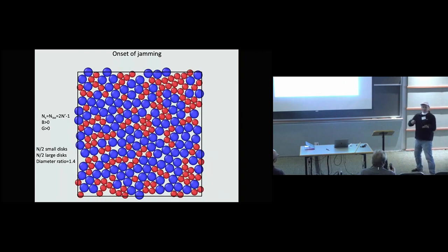Okay, so I went a little fast. They're all growing uniformly. So I make a step, and they all grow uniformly. You could do different models, but the one I'm doing is I allow a little bit of overlap. And then what the computer does is it says, well, I want to minimize my energy, given that overlap. And so they'll move out. But they're only going to move out until there's no energy. I haven't told you what the energy function is, but I'll tell you in a second. But basically, when they're overlapped, there's a repulsive energy. When they're not overlapping, there's no energy. And so right when they all start to overlap is this jamming transition.